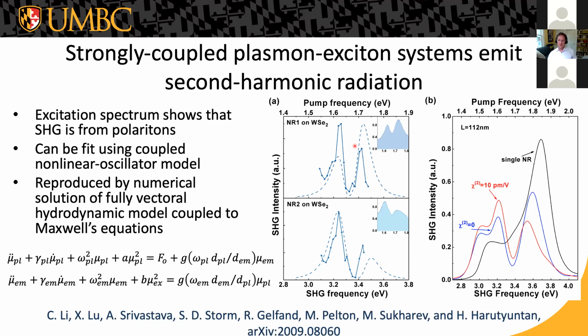If you want to get an estimate of how many excitons are involved, you can compare the coherence area of the excitons to the mode volume of the plasmon, and the mode volume is much smaller than that coherence area. Or you could compare the Bohr diameter in plane of the excitons to the mode volume, and you get a single digit number, not one, but just a few excitons, if you just want to say how many Bohr radii are there within the area of the localized fields. But this is not a single exciton in the sense that the quantum dot is really truly a single exciton system.